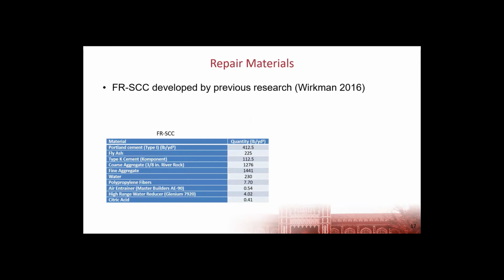The mixture is a Portland cement concrete with fly ash and then type K expansive cement, which is the expansive component. It used a 3/8 inch river rock along with fine aggregate. We used polypropylene fibers. It had entrained air and then enough high range water reducer to get the flowability that we were looking for, which was in the range of about a 28 inch slump flow. We also included citric acid within the mix to control the set, because the expansive component cement does lead to an earlier set time than what we would get with just a pure Portland cement concrete.